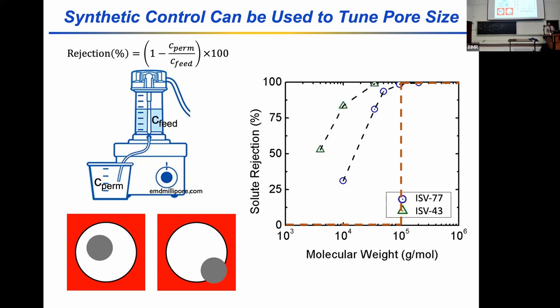And I think most excitingly, when we shift the molar mass of the templating block polymer, we see a corresponding shift in the molecular weight cutoff curves. The one that helps me understand that this is going in the right direction is the one at 10,000 grams per mole. That solute is making it through the 80 kilodalton, the bigger pore size, 75% of the time, whereas it's only making it through the smaller pore size about 20% of the time, right? Its rejection is higher, and so that green triangle is higher than the blue circle at 10,000 grams per mole, which is indicative of the shift in the molecular weight cutoff curve that we would expect.